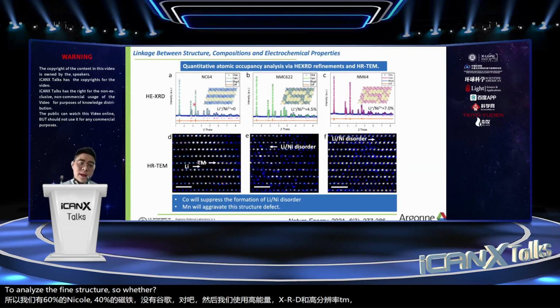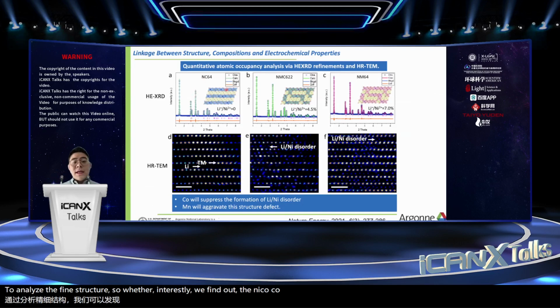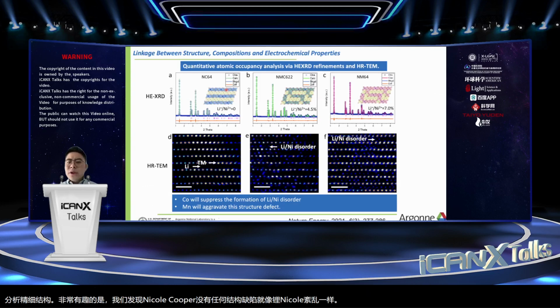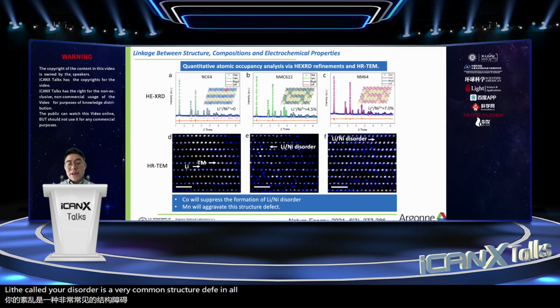So very interestingly, we found out the nickel cobalt doesn't have any structure defects like the lithium nickel disorder. Lithium nickel disorder is a very common structure defect in all NMC cathode materials. It will lower the capacity and also block the lithium diffusion pathway. When we reduce cobalt with the manganese substitution, we will see the lithium nickel disorder increase to 4.5%. And when we completely remove cobalt from the structure, we will have 7% lithium nickel disorder.